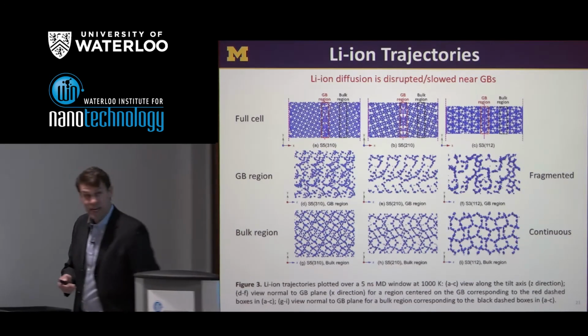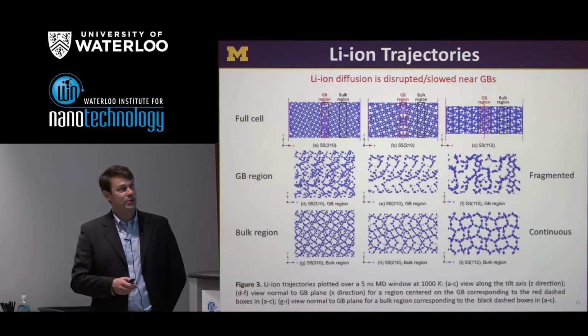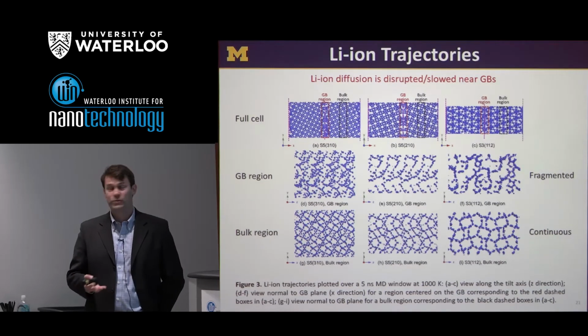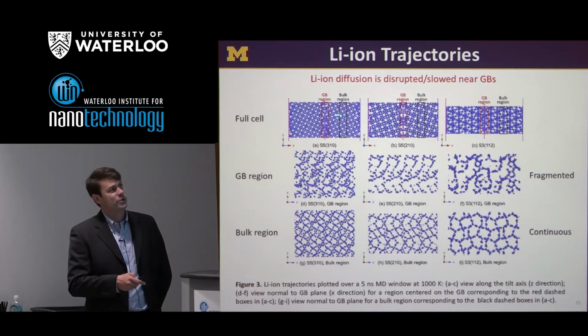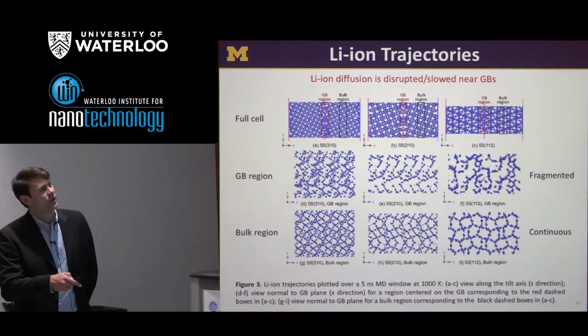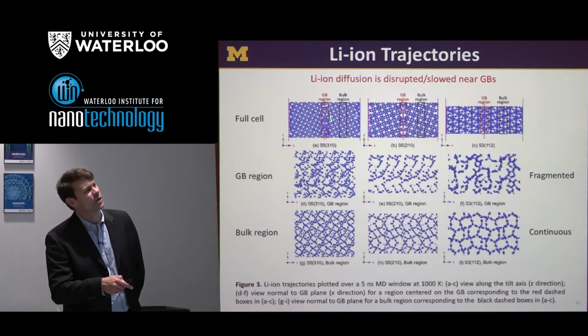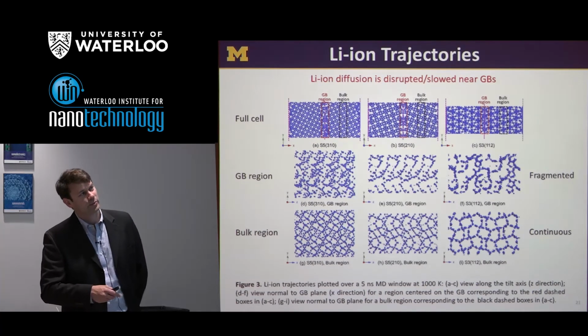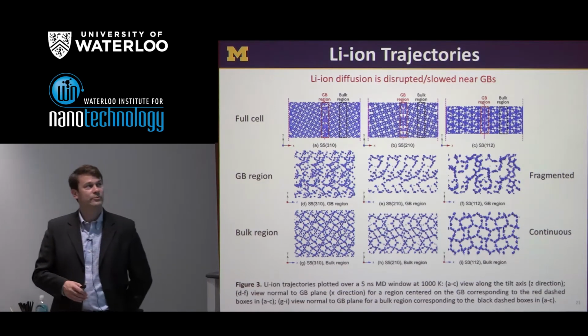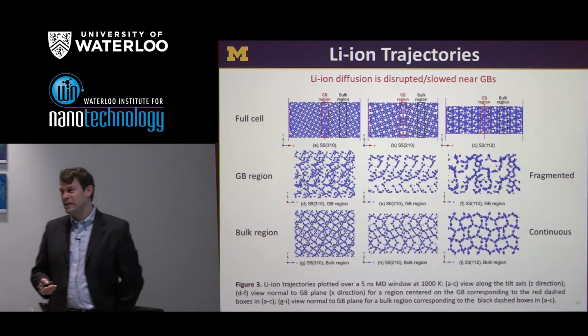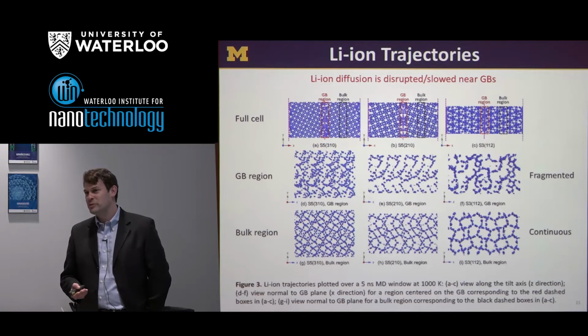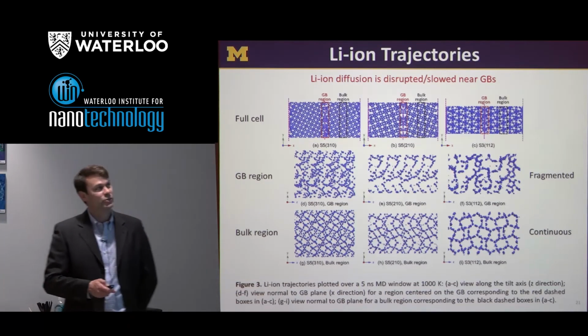What we do then is we take that structure and we run molecular dynamics on it to estimate the diffusivity. And in this case, we're going to focus specifically on what happens in the grain boundary region. So I don't know if you guys can see from where you're sitting, but there's a little red box that's focused on the grain boundary region in each of these cells, and then there's a black box, which is meant to isolate the bulk-like behavior. So one way we can qualitatively assess how rapidly lithium is diffusing is to plot the trajectory of lithium.